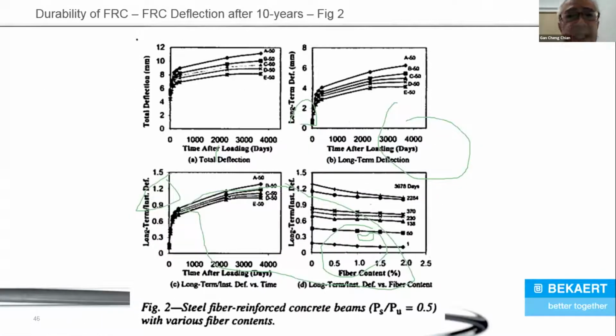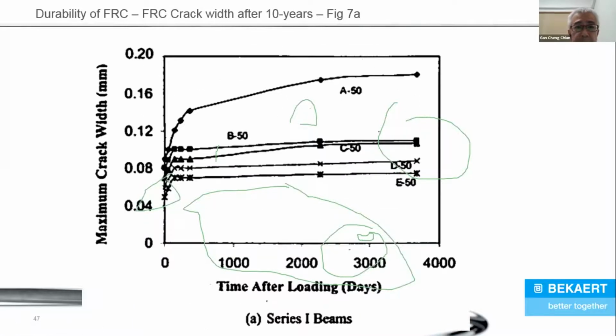And here you will see some results. First of all, they were looking at deflection of the beams after 10 years. Now, you will see the curve might be small, but for those who want more details, I have all the papers, so I can send all the papers to you. A means plain concrete. B, C, D, E means fiber reinforced concrete with different dosages. So E is the higher dosage and B is the lowest dosage. So from this curve, you will see that fiber concrete shows lower deflection than the plain concrete after 10 years. Another one.